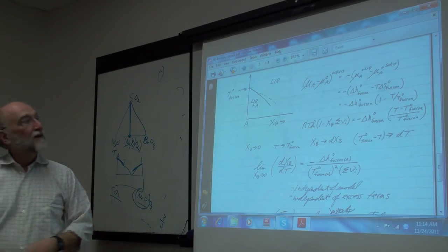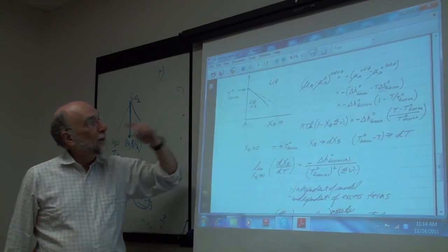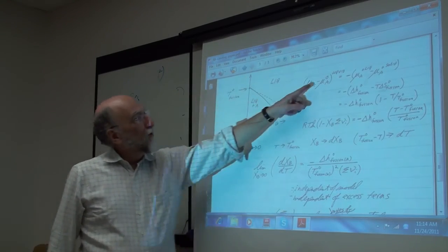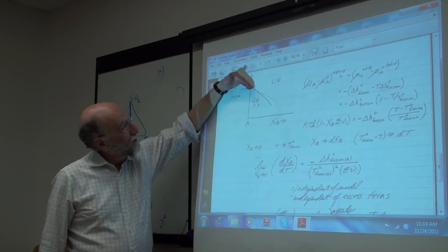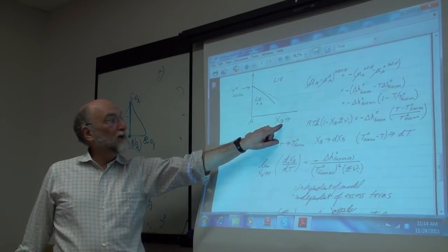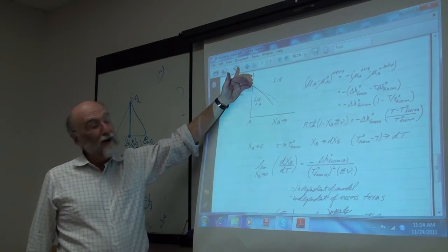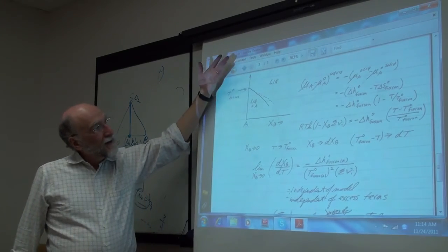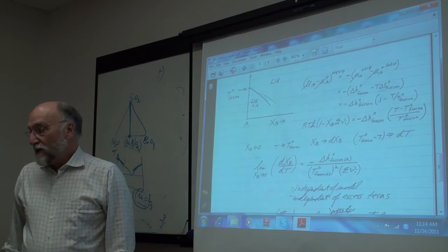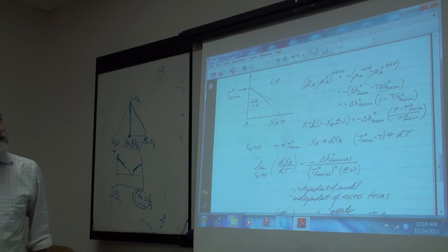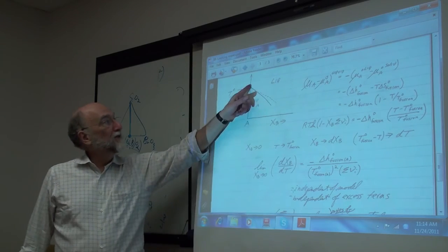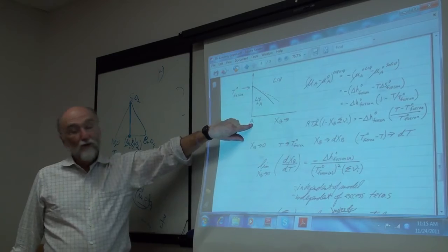It's all based on the fact that the liquidus equation at this end, mu liquid minus mu solid, RT log activity of liquid minus RT log activity of solid, only involves the solvent. The liquidus at the limiting end does not depend at all upon the partial property of the solute. It only depends upon the partial property of the solvent. And furthermore, Raoult's law is obeyed. Okay, so you don't need to worry about the excess terms. But Raoult's law is only obeyed if you take into account the proper number of particles. So when people say limiting system at infinite dilution, infinitely rich system always obeys Raoult's law.